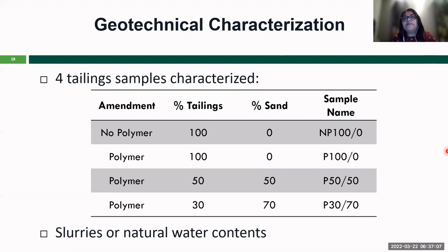4 different types of tailing samples were used because we wanted to check the tailings without polymer treatment. And then we checked the tailings with polymer treatment that we received from the TSRU site. And then we used sand samples, 50% sand samples and 70% sand samples with these tailings. And all those materials were tested for the geotechnical tests summarized in the test summary that I just presented.